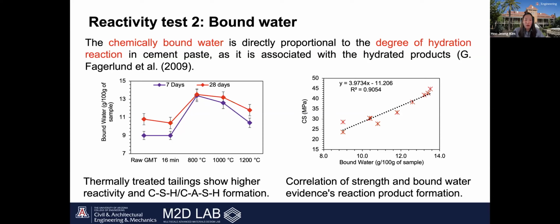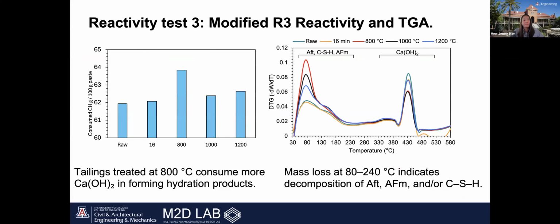And that weight loss tells us how much water was chemically bound. We followed method B of ASTM C1897 standards. And the result shows that the 800 Celsius degree activated sample has the highest amount of bound water, which matches well with the compressive strength results. And this confirms that the thermal activation at 800 Celsius not only improved the strength, but also enhanced the reactivity and the hydration of the tailings.